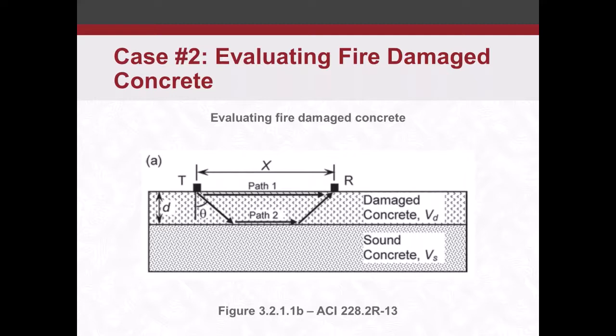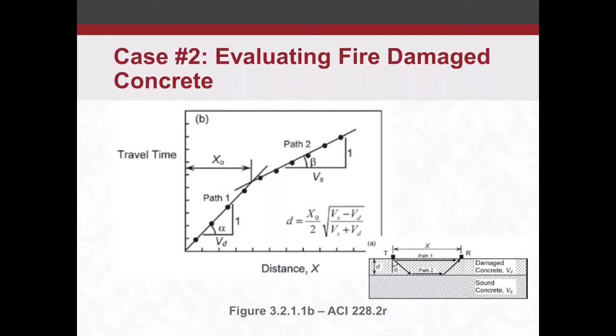And when we plot the travel time versus distance, we should see two very distinct slopes. And the inverse of the slope is the wave speed. So this V sub D is the wave speed in the damaged concrete, the inverse of this slope, and the inverse of this other slope is the wave speed of the sound concrete. So that's V sub D, V sub S.